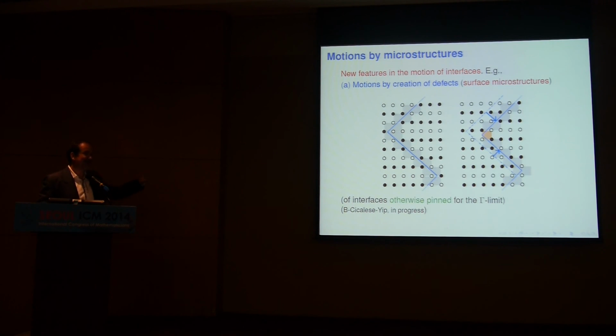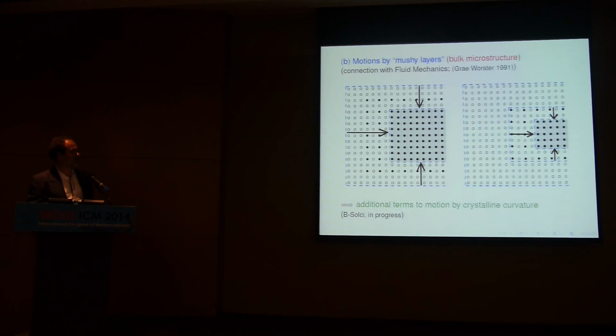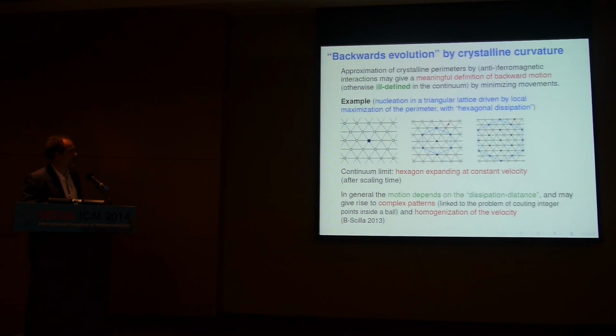I have to say, finally, that you also have interesting things in the evolutionary setting, where you have motion by the creation of microstructure, which can be point defects that move, or bulk defects that are annihilated along the surface. And you can also have a way to define some backward motion by crystalline curvature, looking at minimizing movements for antiferromagnetic materials, which are not possible in the continuum setting.